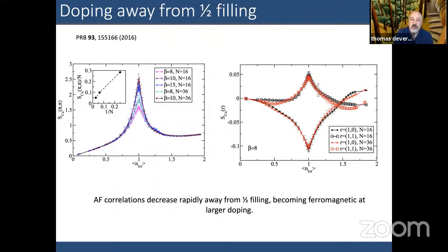And then just moving to magnetism, going away from half filling for both three-band and single-band. This is just looking at the structure factor on copper at momentum pi, as a function of doping for different temperatures on the left-hand side. And you can see a very strong peak at half filling corresponding to the antiferromagnet, which is increasing as system size is increasing. And then it drops away differently, whether one hole dopes or electron dopes. That's a particle-hole asymmetry that occurs coming off of half filling.